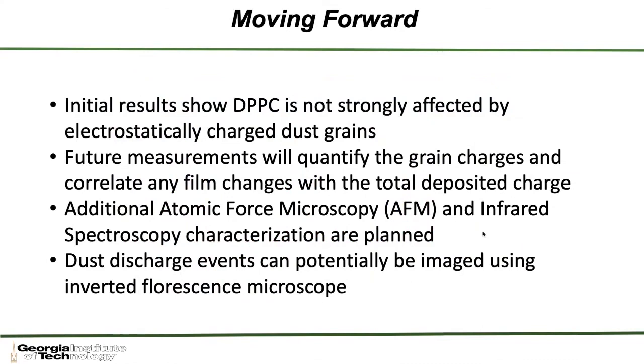In the future, we're hoping to better quantify how electrostatically charged the grains that come into contact with the films are. That just requires measuring basically the charge on those grains, and then doing additional characterization post-exposure using AFM, and also using other techniques such as infrared spectroscopy. And certainly we see that we can get these dust discharge events, and we're looking into different ways of looking at those using fluorescence microscopy, perhaps as a way of being able to, in that discharge vapor, determine some sort of chemistry that's happening.